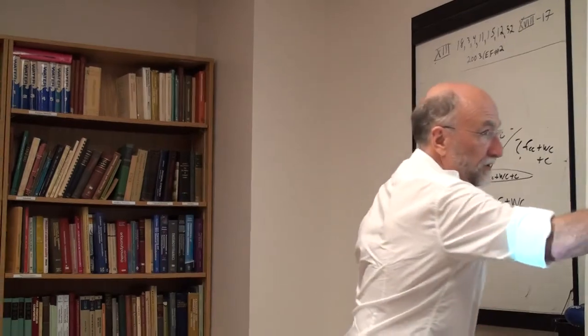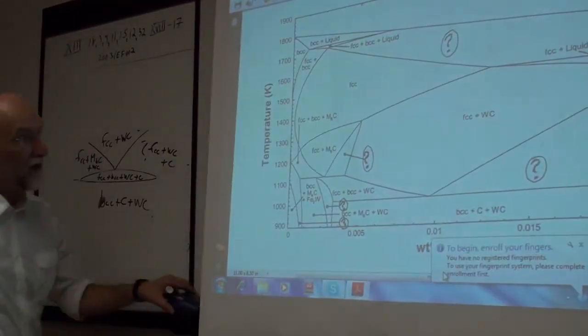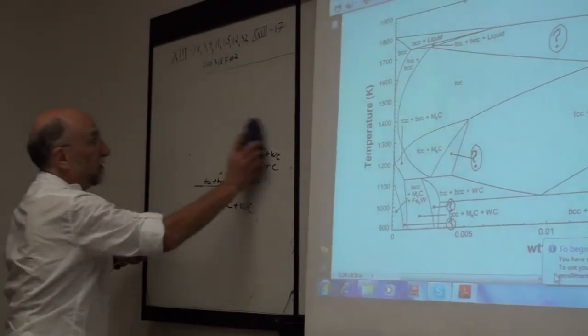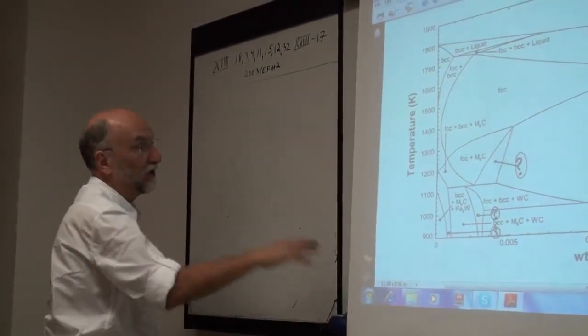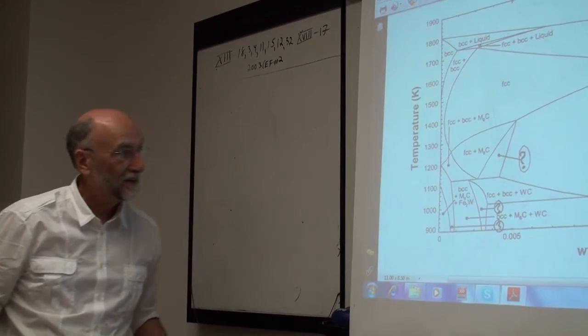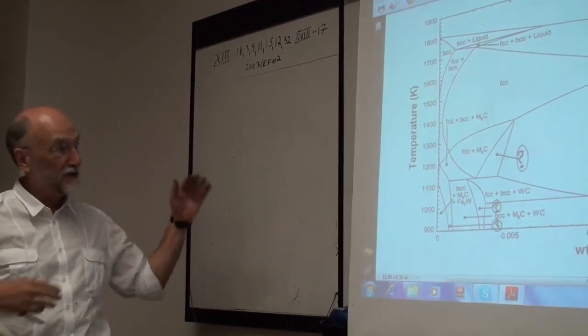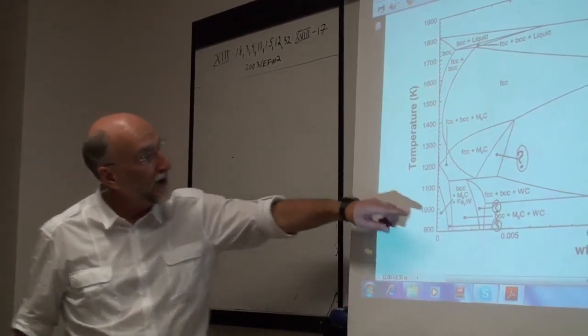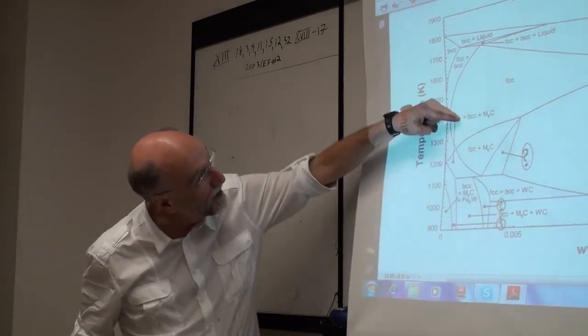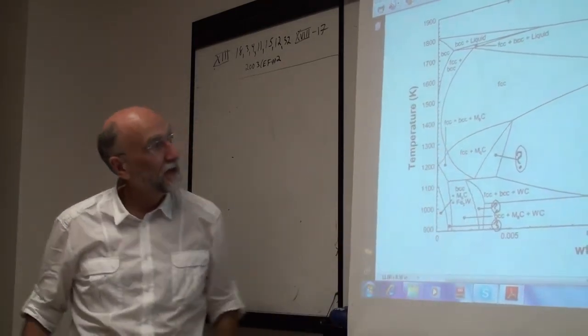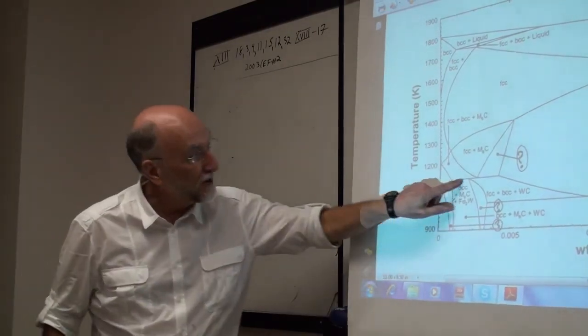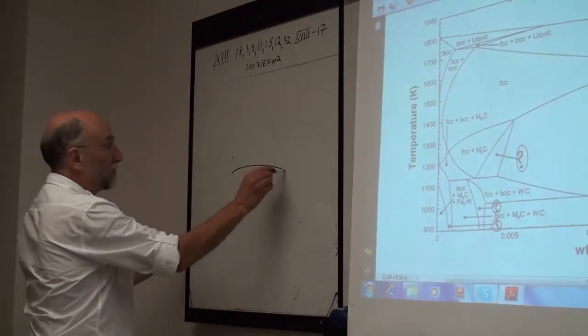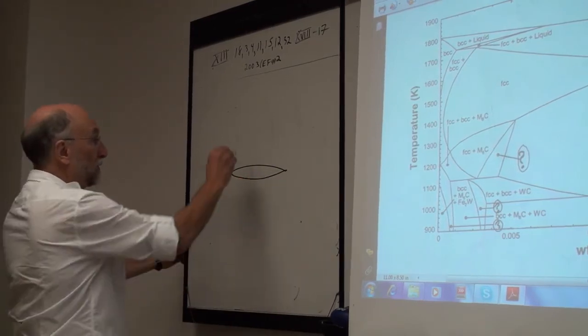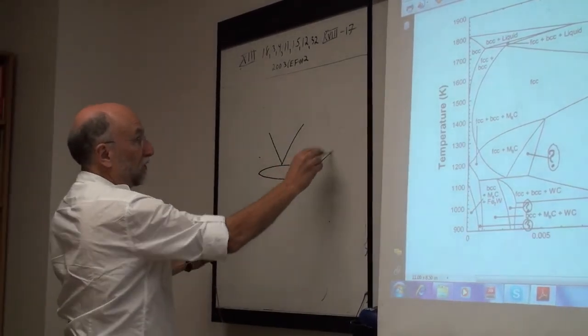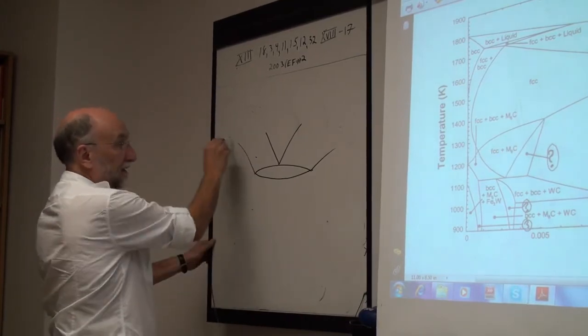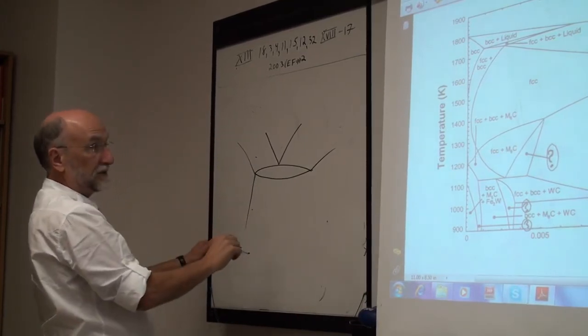Okay, so let's go back now to this horizontal line. Again, that horizontal line is not a phase boundary. Just the fact that it's horizontal at constant temperature tells you immediately that it's not a phase boundary, it's a narrow three-phase region. Or again, you can see it if you go from this region and you cross the boundary here, two phases change. So I'm going to take this line here and again open it up into an artificially opened region, and now we see the nodes go like this.